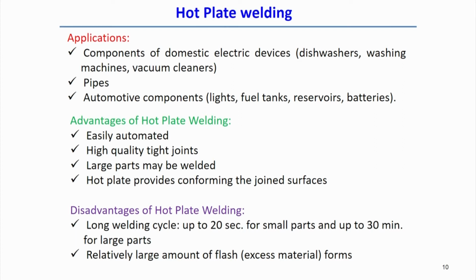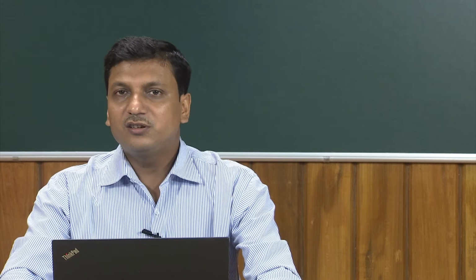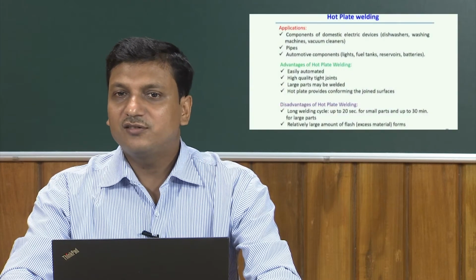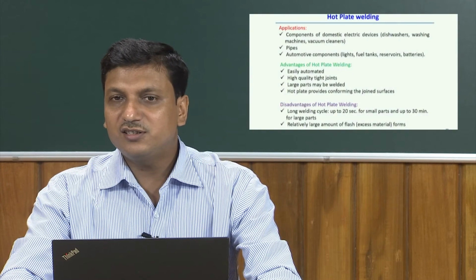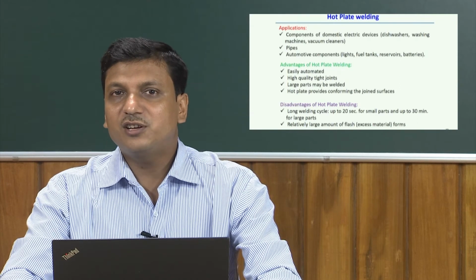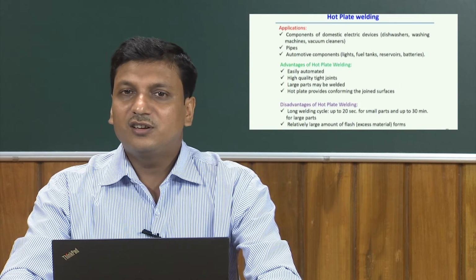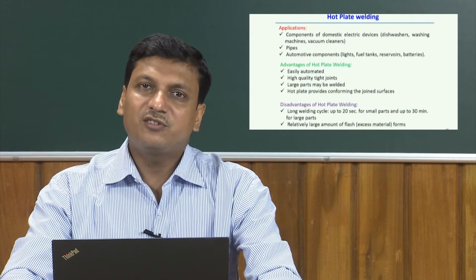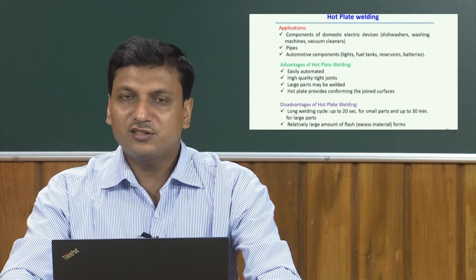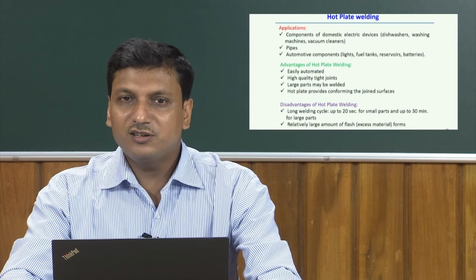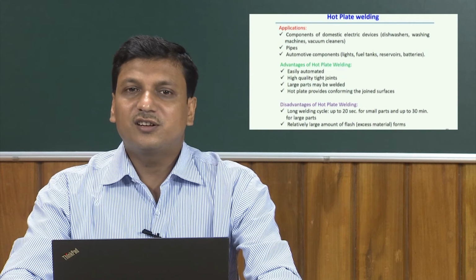So, normally the welding cycle is typically 20 seconds for small parts and up to 30 minutes for large parts. That is the disadvantage: a huge welding time is required in the case of hot plate welding. So, that means the rate of production may not be very good with this welding technique.